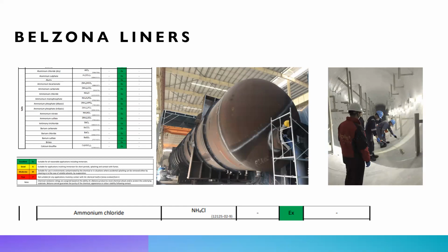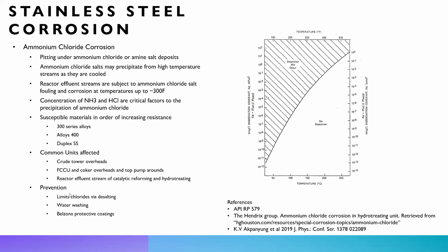So if you do have a service where you're using stainless steel to increase your corrosion resistance, but you're still having some issues due to salt deposits and pitting corrosion, if we can handle the service as far as temperatures and other chemicals involved and pressure, we could be an option to coat that problem area and protect it from further pitting corrosion.